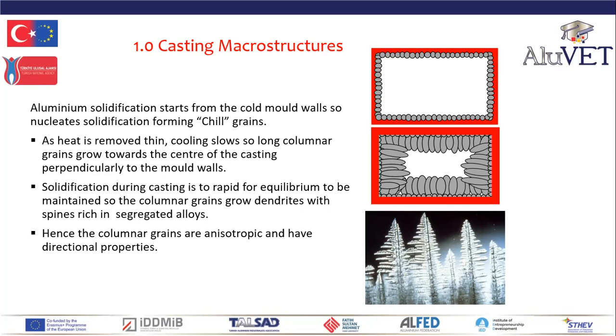Now, the solidification during casting is too rapid for equilibrium to be maintained. By that, I mean, as the liquid cools, the chemistry changes from the walls inwards because the cooling rate is so fast. So the columnar grains grow dendrites. Dendrites are these fingers with spines rich in segregated alloys as they grow.